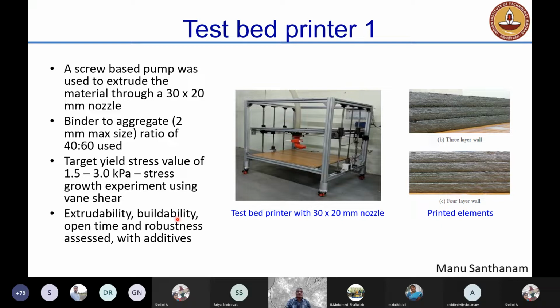Right? You need that because depending on the type of printer that you have, you may have the printing operation going on continuously. And you don't want your concrete to set inside the printer. That will be a big disaster, right? So you need to ensure that the open time is maintained for a long period of time. And robustness is very important because any small change in material characteristics should not affect the quality of the printed